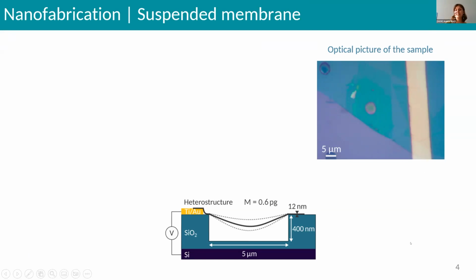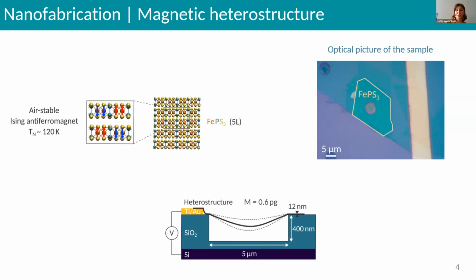So how do we make this sample? So in a clean room, we exfoliate the materials of interest, and we exfoliate different materials that we can stack together with the pickup technique, and then we transfer this stack over a hole to obtain such a nanodrum. So the first material we chose to study is FePS3, which is an air-stable Ising antiferromagnet, and its phase transition temperature between its paramagnetic and antiferromagnetic phase is about 120 Kelvin.